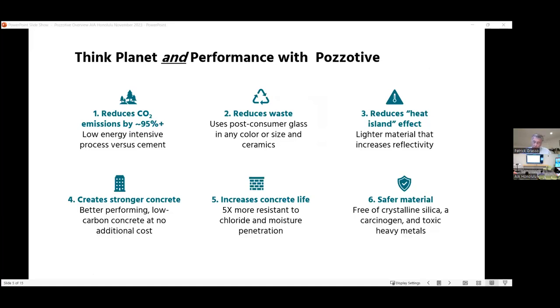Well, the challenge to go back to bottles is that you've got to color separate. You can only do that to a certain size, and you have to get ceramics and porcelains out. Ceramics and porcelains, as you may know, have a different melting temperature when you try to send them back to bottle manufacturing. It causes chaos in the furnaces. The fact that they are Pozzolanic and we are not melting, we are just cleaning and grinding, allows us to keep those in the mix. And again, we can use any color and any size. So really no glass has to go to waste in our process.